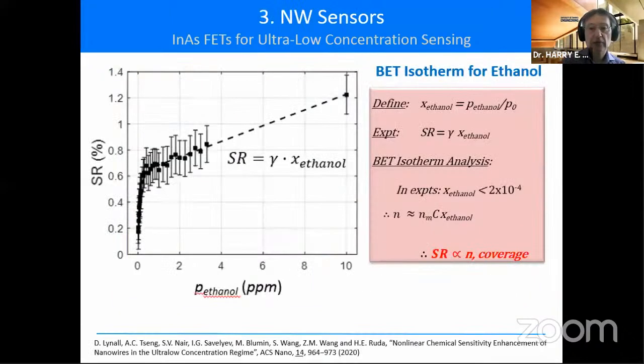All right, so let's go back to the data that I showed you for the ethanol adsorption, physisorption process. So the sensor response is shown on the left-hand axis, and the partial pressure of ethanol in ppm is shown on the horizontal axis. And we define some parameter x, which is that ethanol partial pressure in relation to the saturated equilibrium pressure of ethanol. And in these experiments we're looking at here, a few ppm would correspond to 10 to the minus 4 or less for that value of x.